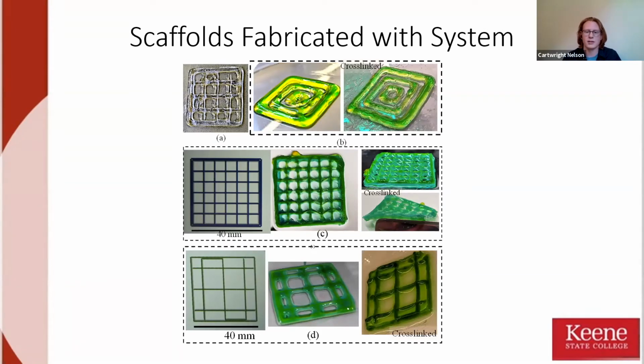So these are some of the scaffolds that were printed using the system. You can see in the middle, it is cross-linked, and it's kind of hard to tell, but you can see how different layers are different colors, I think the bottom is green and the top is blue. And then above that, there's a not cross-linked and a cross-linked version. So these are just different scaffolds showing that it can print different layers with different materials and transition between the two without stopping the print.